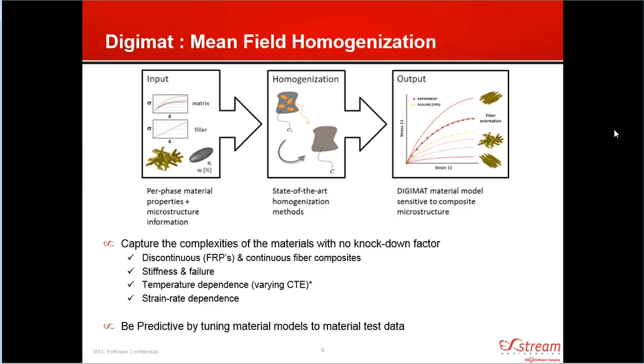So we can go back to our input and we can vary that fiber orientation, and we can predict the composite response as you see in the top curve, where the fibers are very aligned in the direction of flow, so similar to the gray curve on the last slide, to the scenario where the bottom curve where the fibers are very transverse to the direction of loading, and then anywhere in between there, where you have randomly aligned fibers, or you have partially aligned fibers, or just really a wide variety of scenarios there.